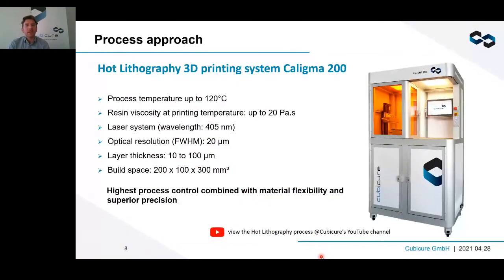Our first system, we introduced that in 2017, is our Caligma 200 machine. So this machine is supporting this hot lithography process window I just described, and it's working with a 405 nanometer laser with a very high resolution. So we're talking about 20 microns in the laser spot, and of course you can choose now in the layer thickness roughly between 10 and 100 microns, and this allows you to print fantastic structures with very fine details over a quite large building platform. So 200 times 100 millimeters, still small for industrial scale, but quite big when it comes to this tremendous resolution. If you're interested in the details of the process, please maybe after this session, take a look in our YouTube channel. There we have a nice CGI video where you see the process working in detail.